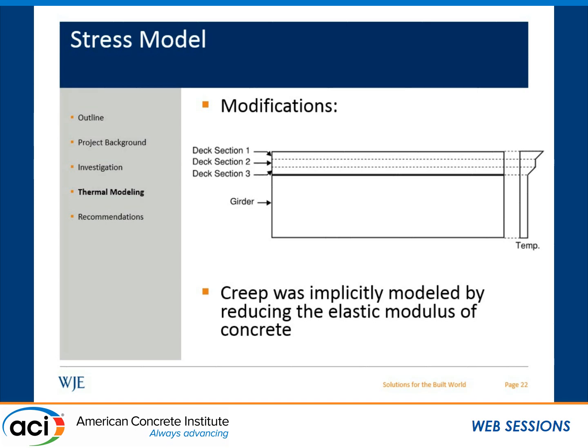And that's because if you assume the full elastic modulus, without accounting for creep, it's essentially like saying you're taking your concrete and placing it in a freezer. It's a shock load. It's going to contract much faster. But these are more gradual temperature changes. And so the effect is not going to be as severe as if you were to take hot concrete and stick it in a freezer. It's going to change gradually. And so you can accommodate this by reducing the elastic modulus. So at early ages, we assumed the elastic modulus was half. At later ages, we assumed it was 1/3 of the actual value.